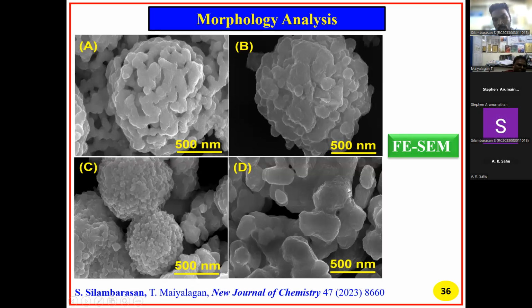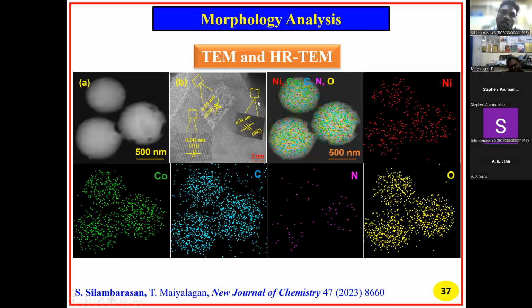And compared to sample 3, the porous sphere structure is breaking here, because with increasing concentration, the spheres automatically break. Otherwise, all these spheres are uniform, as we confirmed in the SEM analysis. Next, the TEM and HR-TEM analysis. Here, figure A is the nickel doped cobalt oxide with nitrogen doped carbon sphere, and figure B is the lattice spacing calculation, with values of 0.29 nanometer and 0.24 nanometer.